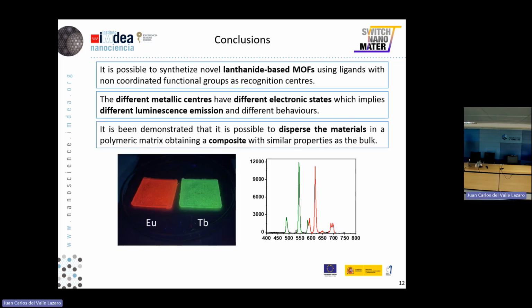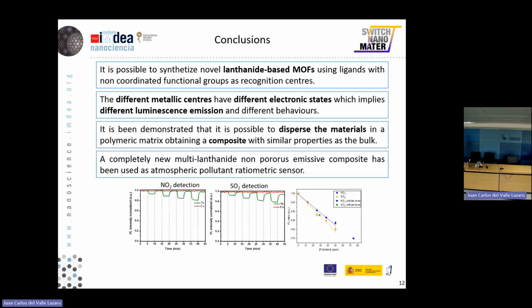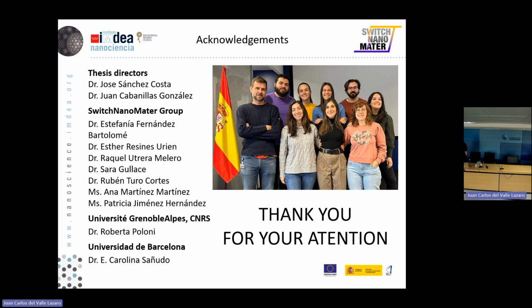Finally, it's been demonstrated that it's possible to disperse these materials in a polymeric matrix, obtaining a composite with multi-lanthanide emission properties similar to the bulk. And this material can act as a ratiometric sensor for the two different atmospheric pollutants, with a low limit of detection for SO2 and NO2.